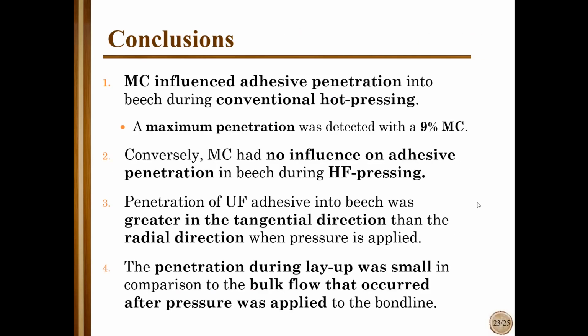Some conclusions. In terms of moisture content, there is certainly a significant impact of moisture content on adhesive penetration when we talk about conventional hot pressing. Maximal penetration was detected at medium moisture content of 9%.